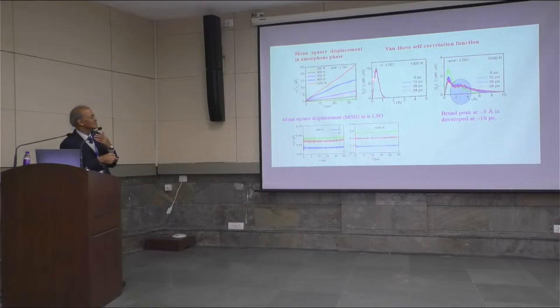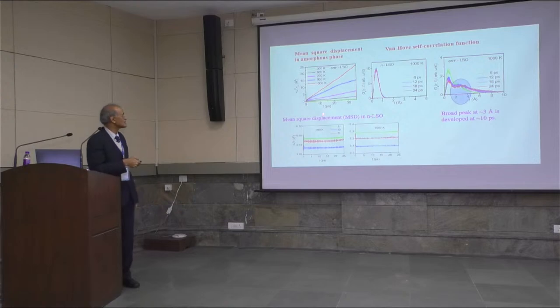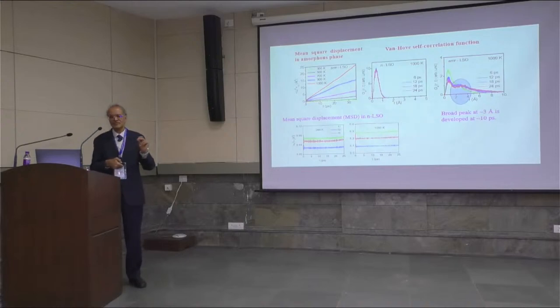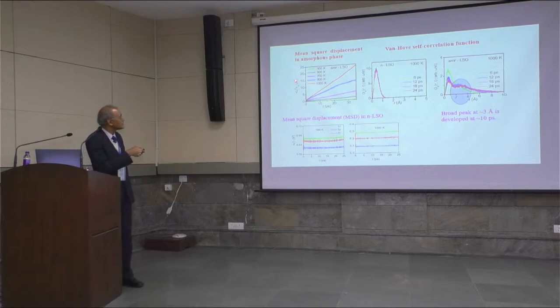Now you can also, with a simple molecular dynamics calculation, calculate the mean square displacements of atoms. In a crystalline material, the mean square displacement does not change with time. These are just the thermal vibrations. So the mean square displacement is practically independent of time, and it increases with the temperature. But this does not indicate diffusion. However, if the mean square displacement increases with time in a molecular dynamics simulation, then that indicates diffusion. So in this amorphous material, the diffusion coefficient is proportional to the slope of this function. So from that one can identify this.